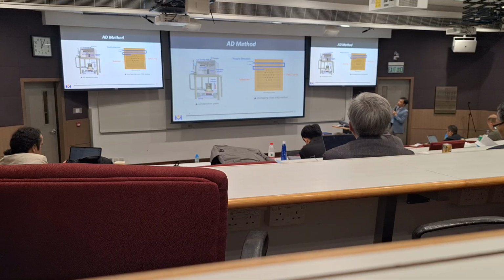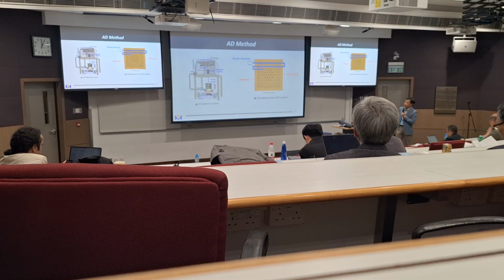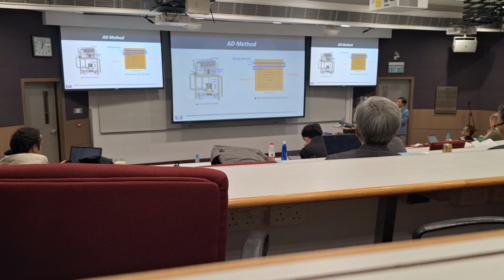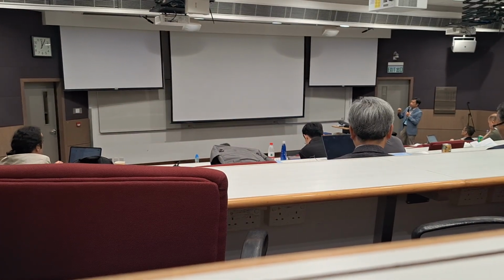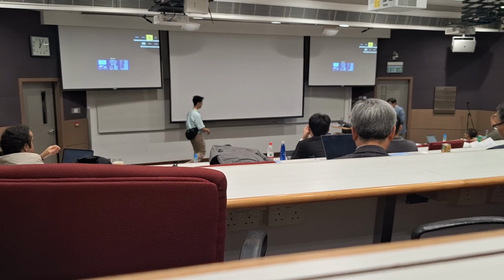And this is the aerosol deposition method we developed in my lab. This method was originally invented by a Japanese researcher around 25 years ago, and we built a machine in my lab by ourselves, and it can grow very dense piezoelectric ceramic film. The thickness we can grow is typically 5 to 12 microns.